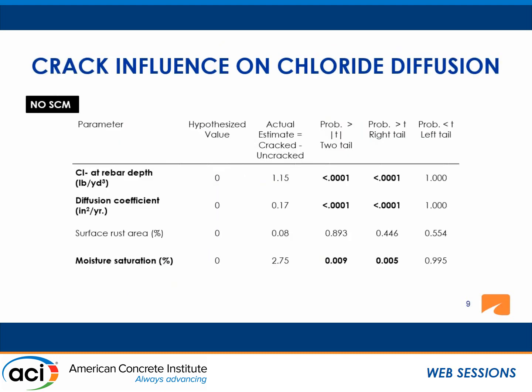So in order to compare the chloride diffusion between cracked and uncracked, we did a pairwise statistical analysis using Wilcoxon signed rank test, because these were not normally distributed. And the hypothesized value is actually the difference between cracked and uncracked chloride diffusion values. But the actual values are shown on the third column.